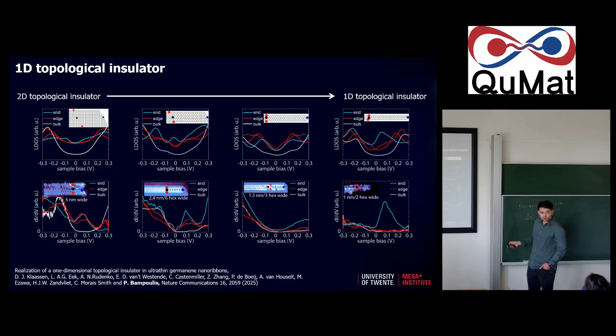Over here, you have something very similar. It's a little bit more complex because you have spin-orbit coupling, you also have staggered mass. But if you take the example over here of a 3 hexagon wide nanoribbon, now you have an odd number of hexagons, there is no end state. And you can see that there is no end state both in theory and in the experiment. So that also matches quite well with the expectation.